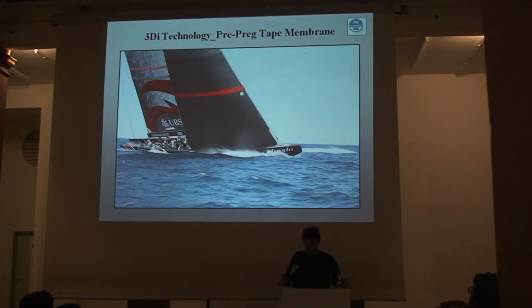So that's our original technology that, as I was saying, was 22 years old, 3DL for three-dimensional laminate. And in the last few years, we, along with a couple of different Swiss guys, why all the technology in our industry is originating in Switzerland, I have no idea, but it has been. So we came up with a new technology where instead of laying yarn tows or fiber tows on films in a load path or structural anisotropic orientation, we're going to make sails completely out of pre-impregnated fiber tape. So there would no longer be any film or any substrate. So here's an example of a 3DL sail in the back, and you can see the classic fiber architecture in the orientated direction. This sail is made out of pre-impregnated tape, just like any other race car, airplane wing, and it's fiber and resin only. There's no longer any film or any substrate there.